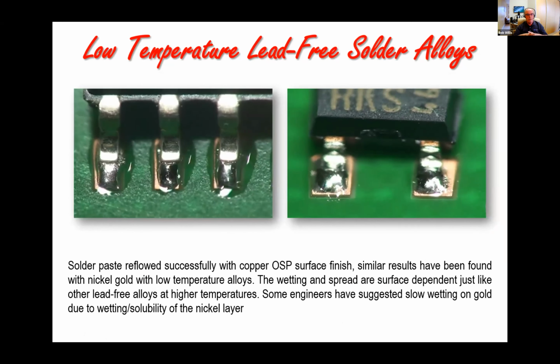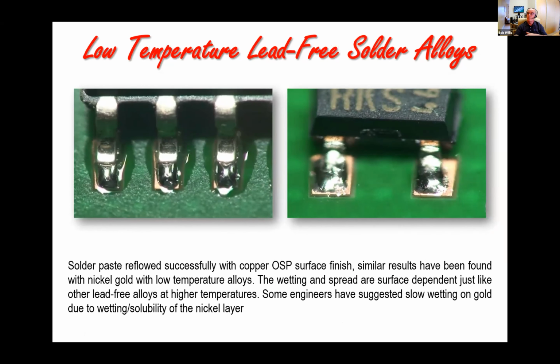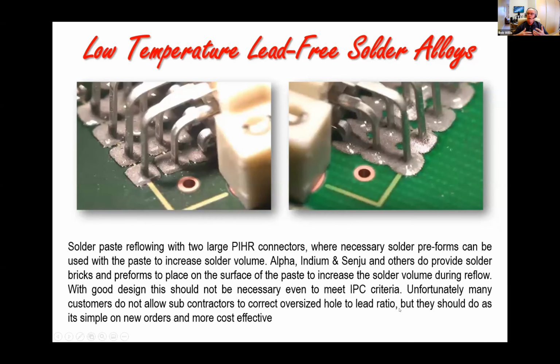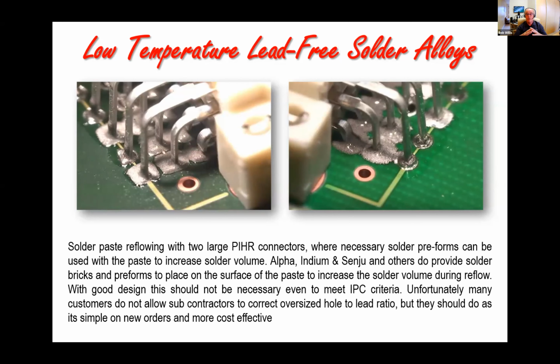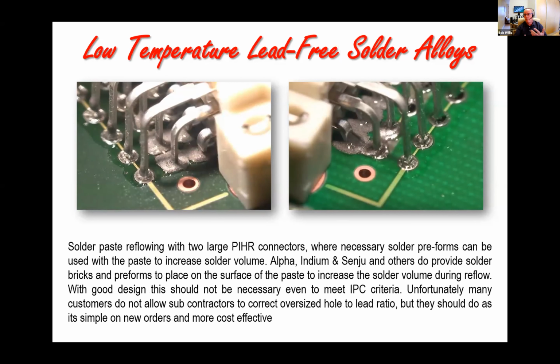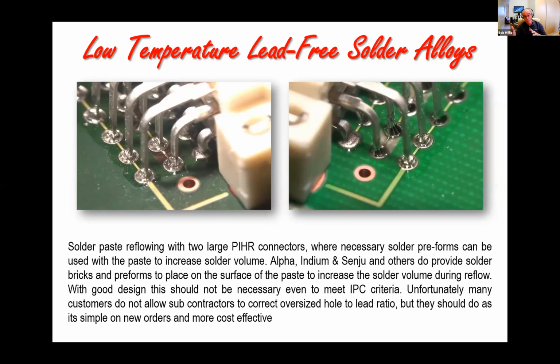You can see the joints forming perfectly. But always remember that with copper OSP and tin also, you quite often see some evidence of the original pad surface still visible. That comes down to the volume of paste you put on to start off with. But they're perfectly good and reliable interconnections that we show illustrated there. I mentioned the benefits of using this lower temperature material, as other engineers have highlighted, on intrusive reflow or pin in paste reflow. And these are just examples of the low temperature material actually being used on connectors, which can be obtained as a lower temperature version.